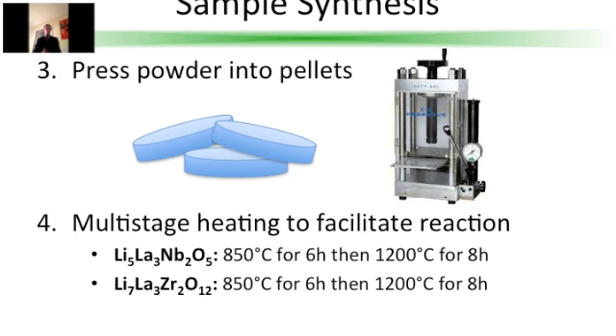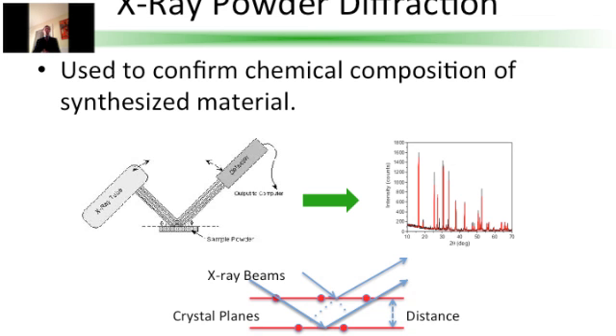So after heating the samples, heating the pellet, I confirmed whether the sample I synthesized was in fact phase pure lithium lanthanum zirconate or lithium lanthanum niobate by using a standard technique called X-ray diffraction. X-ray diffraction uses a machine called an X-ray diffractometer, which shoots a monochromatic, meaning a single wavelength, X-ray beam at your powder sample. Now, when the beam hits the sample, it is reflected by the atoms in your sample, and a detector then measures the intensity of the reflected beam.